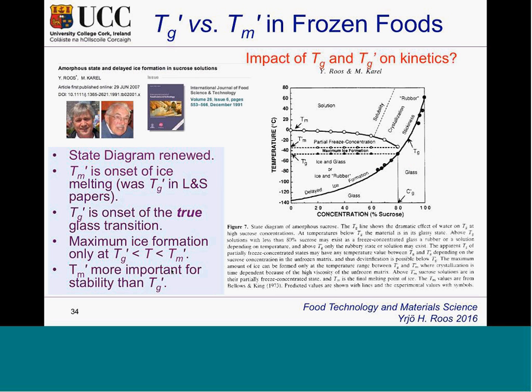We did a lot of work on freeze concentration, and we related Tg and Tg prime on kinetics with Professor Marcus Karel in the early 1990s or late 1980s. And we did quite substantial work on the glass transition of sucrose to show how the glass transition actually happens, followed by melting of ice in freeze concentrated systems. If you have a little time, you could look at this paper and see how the melting is actually corresponding to the Tg prime population, by Harry Levine and Louise Slade. The prime here is the onset of the glass transition.